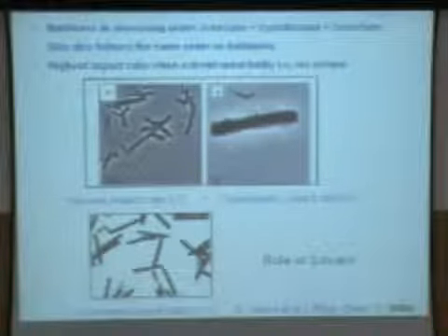So, if you go from bulky hydrocarbons to less bulky hydrocarbons, then the surfactant aggregates which form an interface between the water inside and the solvent outside get affected, and the dynamics of intermicellar interaction gets affected, and hence the aspect ratio can be varied using the solvent.